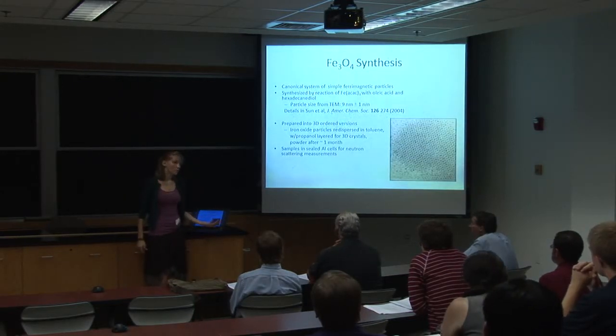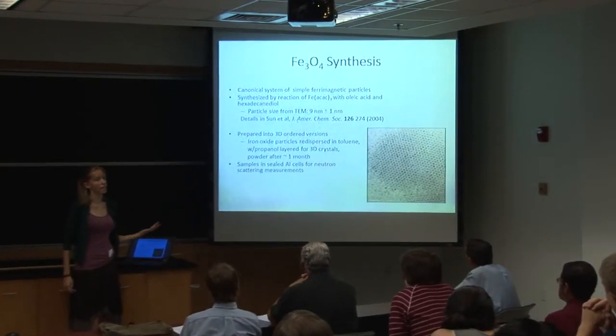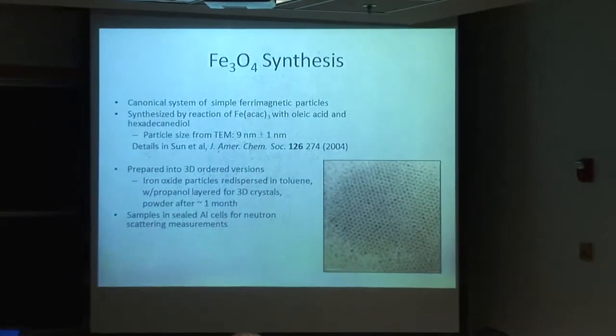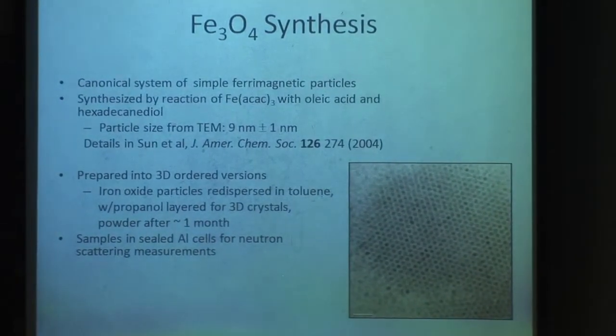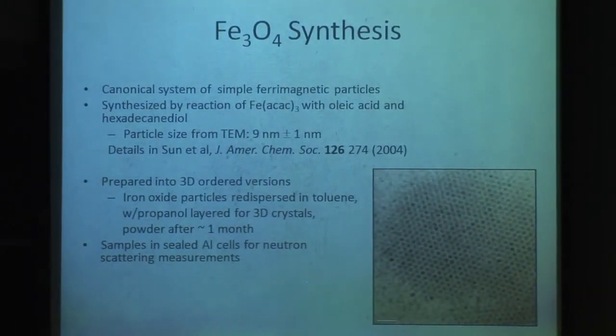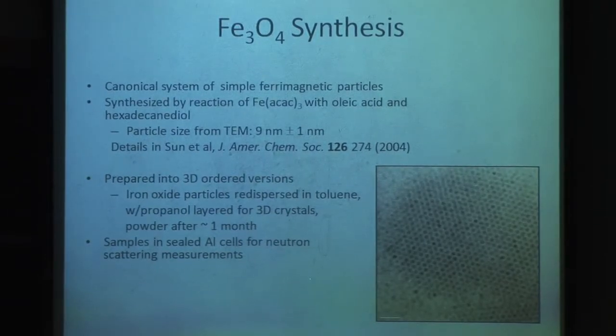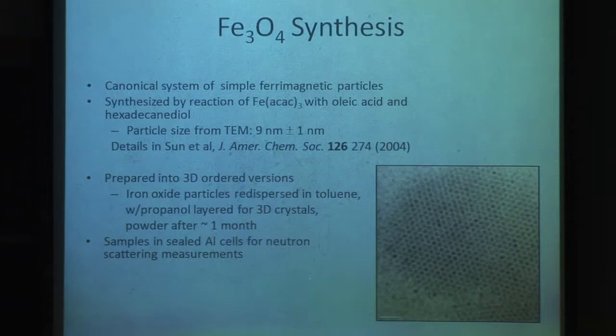So we've been working with a system of iron oxide particles. This is a canonical system of a simple ferrimagnet, which means it's just one chemical system as opposed to a core of one type of metal and a shell of something else, or something like that. These were synthesized by reaction of an iron precursor, and we found that they had a particle size of about 9 nanometers through a TEM image, such as the one shown here. We prepared these into a 3D ordered version by redispersing our chemical solution of iron oxide particles into toluene, and we were growing them into 3D crystals. And we grew them for a month and got them into a powder. These samples were sealed into aluminum cells for our measurements.